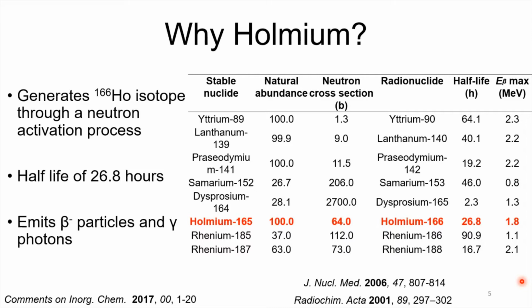As you can see, the neutron cross-section right here in the middle tells you how easy it is to activate this material. While Holmium doesn't have the highest number, the natural abundance for the isotopes with the highest numbers is really low, which means that if you want really high purity materials containing these isotopes, you will spend a lot of money. Holmium is one of the few that have 100% natural abundance. And compared to other 100% natural abundance elements, like yttrium or praseodymium, their cross-section is lower. So Holmium seems to be one of the better suited elements to work with.